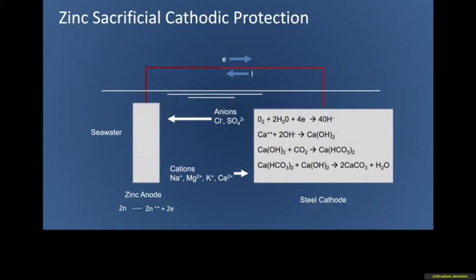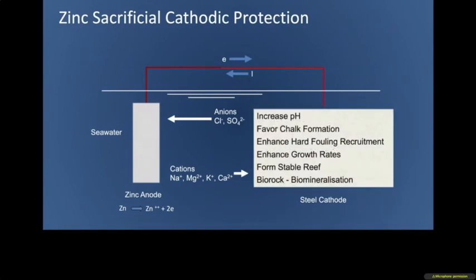And basically, for cathodic protection, I have a zinc anode. The zinc anode corrodes. It provides electrons to the steel cathode. At the steel cathode, you get a reduction in oxygen. You get an increase in pH. And you typically get calcium carbonate and magnesium carbonate. You get chalk formation. One of the interesting things from a biofouling point of view is that increases in pH typically favor the development of benthic organisms that create calcareous shells for their protection. So it should, in theory, enhance hard fouling recruitment and enhance growth rates. It forms a stable reef.